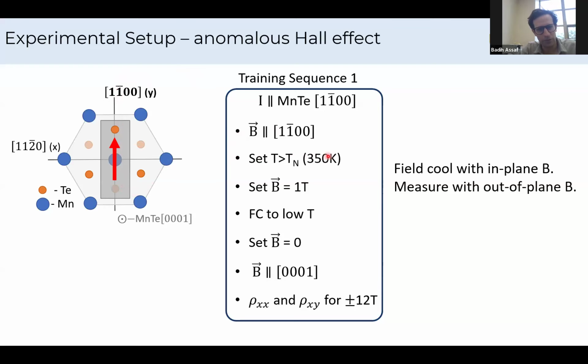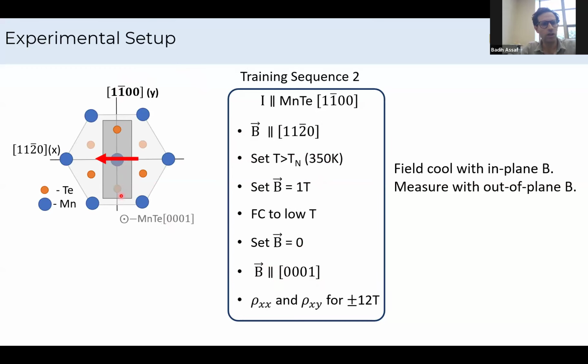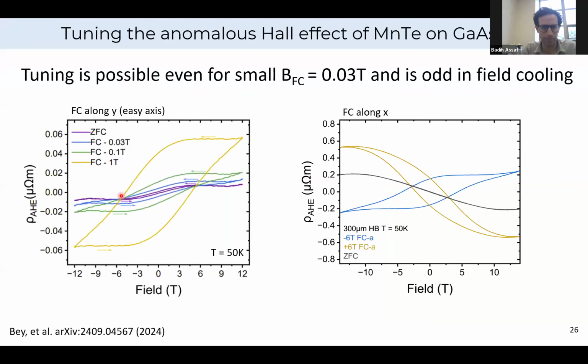We warm up to the Néel temperature, and then we cool down under 1 Tesla, more or less sometimes, all the way down to 2 Kelvin. And then we shut off the field, we saturate with B applied along the C-axis, and then we measure. And we can repeat the sequence for a field cooling that's in the plane, either along Y, along the easy axis, 1, 1 bar 0, 0, or along one of the hard axes, the X direction, 1, 1, 2 bar 0. What we find is pretty impressive, actually.